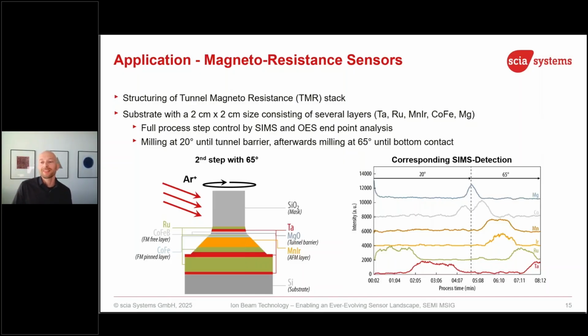And for that reason, this 2-step processing is very common for ion beam etching, to make sure that, together with the wafer rotation, we don't have any redeposition on the sidewall, and we have finally a nice sensor.